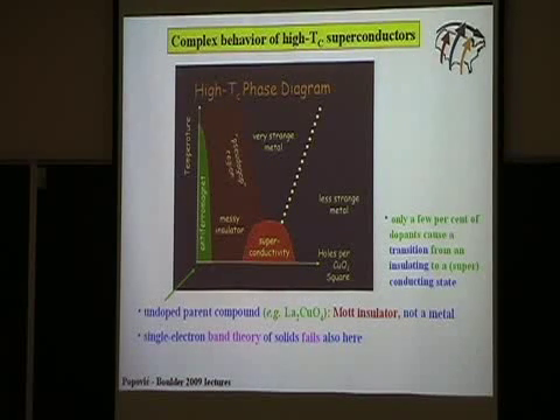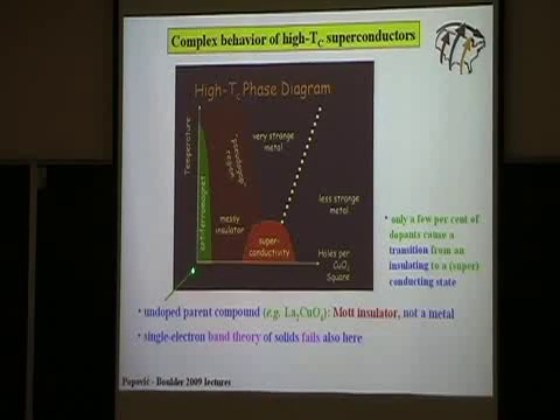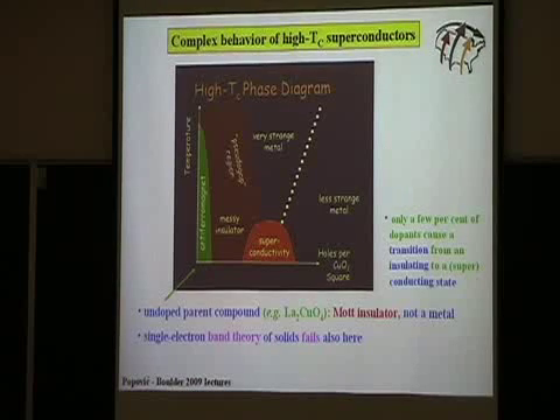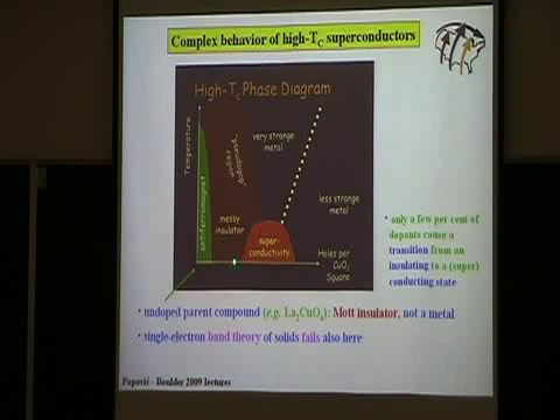So in these materials, people start from an insulator again, and they dope it, and the insulator is an antiferromagnet. With a very small level of doping, 2 or 3%, the long-range antiferromagnetic order is lost, and then when the doping is only 5 or 6%, the material becomes a high-temperature superconductor. So it's a very dramatic change of behavior over a relatively narrow range of doping. Between these two phases, there is a regime that we are actually interested in.